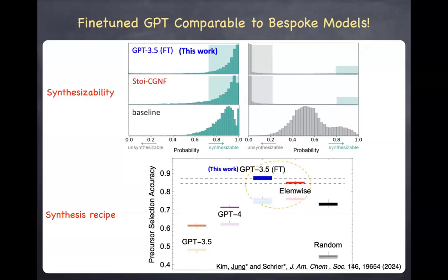And down below, you have the synthesis recipe prediction results. And again, GPT 3.5 fine-tuned and Elemwise, which is the bespoke model that I talked about earlier that is based on template definitions for the precursor selection. And again, you see that the Elemwise predictions and GPT 3.5 fine-tuned are pretty comparable. We were quite surprised to see both of these results because GPT fine-tuning is very simple. All you need is some text prompts and fine-tuning. It doesn't cost much. It costs less than $50 for the fine-tuning process.